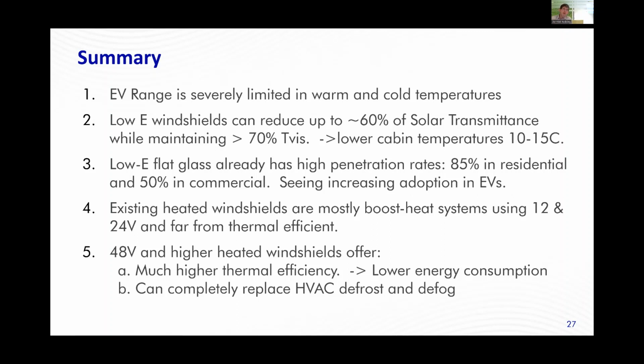And the low E glass has already high penetration rates in residential and commercial. We're seeing increasing adoption in electric vehicles. Fourth, the existing heated windshields are mostly boost heat systems using 12 and 24 volts, and these are far from thermal efficient and cannot replace defrost or defog. As we have more options to tap into higher voltages like 48 volts, we can get higher thermal efficiency that leads to lower energy consumption and greater EV range. And these can completely replace the HVAC, defrost, and defog functions while keeping the HVAC system there for cabin heating and cooling.